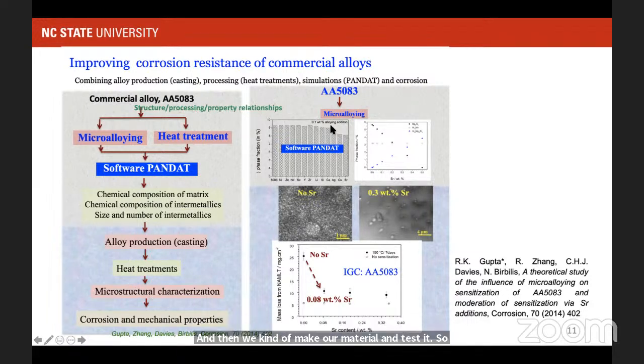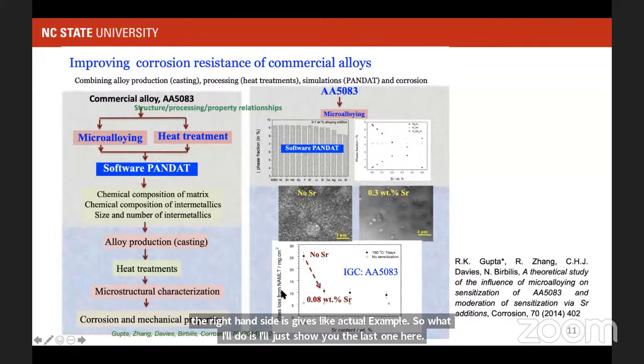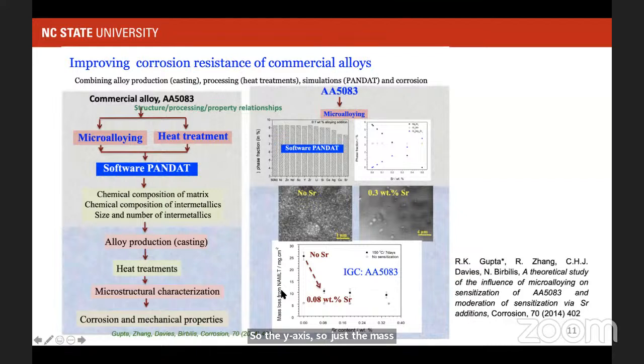So here, on the right hand side is one example. The left hand side gives us the strategy, the roadmap, and the right hand side gives an actual example. I'll just show you the last one here. The y-axis shows the mass loss, which is a measure of the corrosion. With this approach of thermodynamic calculations, we predicted that strontium could be one of the very useful elements in avoiding all these corrosion issues.